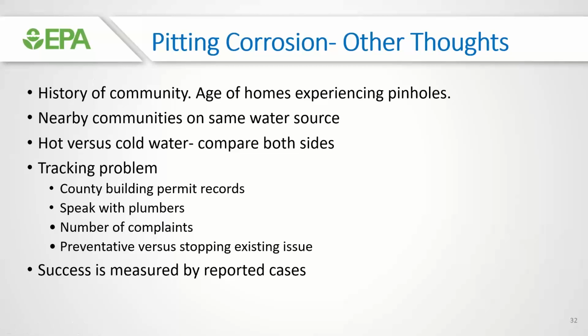So some additional thoughts. History of the community is really important. Age of homes experiencing pinhole leaks in the community is really important. I get this all the time. We have this community, and there's only one part of the community that has a problem. Well, 9 times out of 10, it's the part of the community that was built most recently. The older part of the community had a history of different water quality changes over the years, and those pipe scales developed in a different way that made them protective, we'll say, to the current water chemistry, whereas the newer homes, not so much, right? They saw this new water, the problem water, from the get-go.